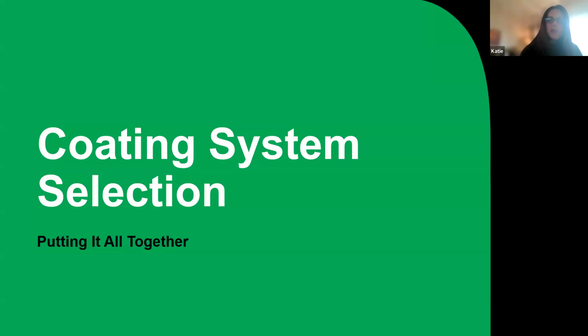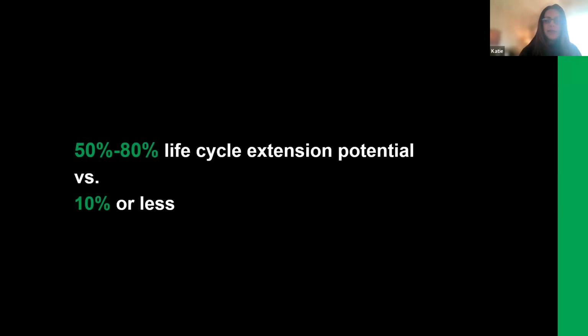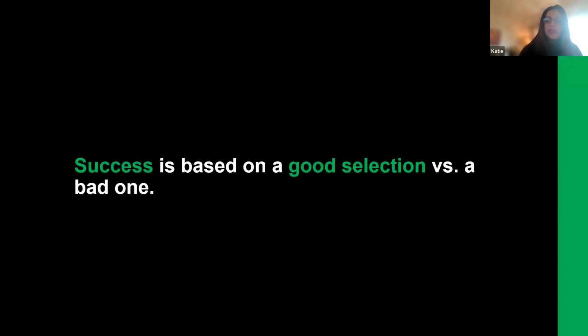So let's go into the coating system selection. This is the fun part. This is where we put all this information together. And as we mentioned from the start, it's the most important piece to reaching our goal of maximizing our service life, which is how we add value, the whole reason that we're here. So remember these stats, the 50 to 80%. It's the coating's life cycle extension potential versus 10% or less. So why the big swing? In years of service, this could be the difference between 10 to 16 years of additional service compared to 1 to 2. That's huge. The success of us extending that maintenance cycle and maximizing the service life is based on the good coating selection versus a bad one.